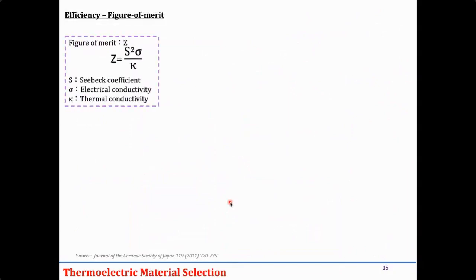So how is the thermoelectric power generator categorized and how can the efficiency be calculated? Here we can see there are four different parameters. One is Z, which is the figure of merit, which shows the efficiency of the device. And then these three parameters: S squared, sigma, and kappa. S is the Seebeck coefficient, sigma is the electrical conductivity, and kappa is the thermal conductivity.